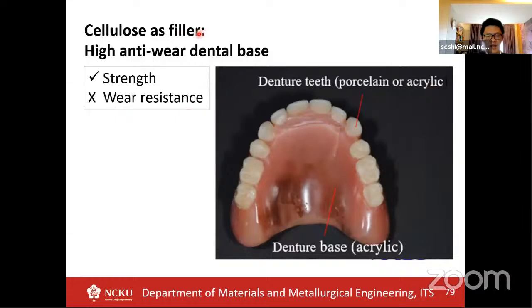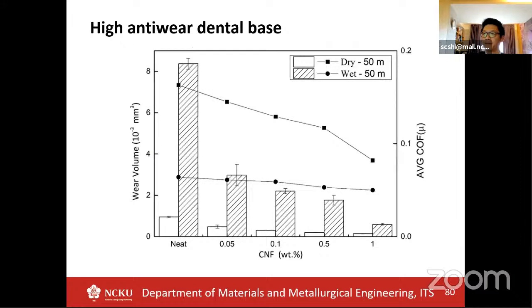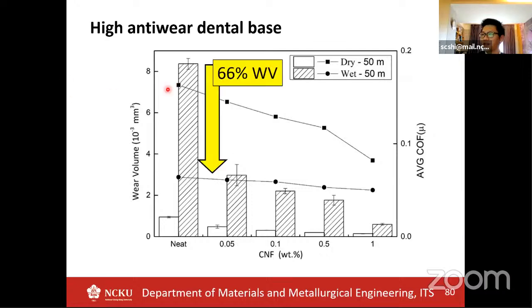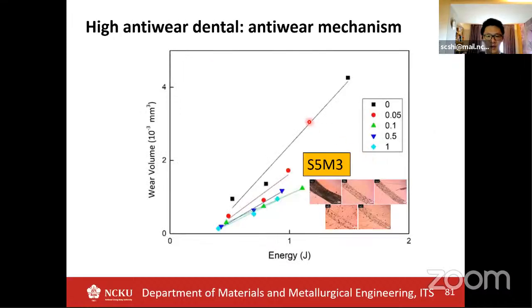And the second example is that with cellulose as a filler, we can have a high anti-wear dental base. The dental base is over here. Normally an acrylic material is used for that. Acrylic has good strength, but it's so brittle that the wear resistance is really bad. So in this case, we just add CNF into the PMMA. We can see the wear volume dramatically decreases by 66%, and the coefficient of friction decreases slightly.